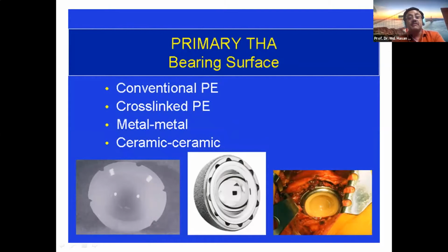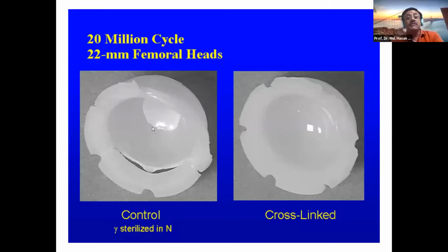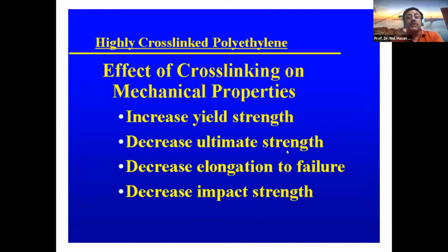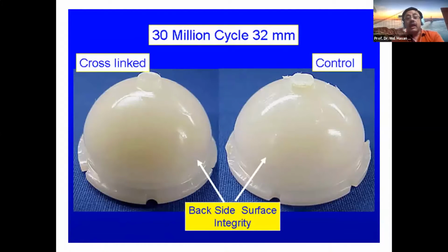So here see, this is the conventional polyethylene. There is wear and tear, and this is cross-linked polyethylene. So the effect of cross-linking on mechanical properties: increase yield strength, decrease ultimate strength, decrease elongation to failure, and decrease impact strength. And this is the backside of